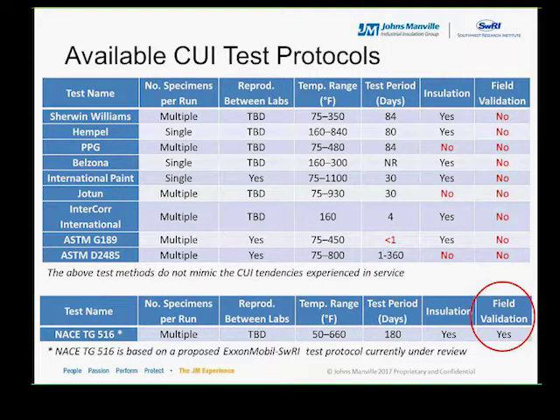Recently, ExxonMobil partnered with Southwest Research Institute to develop a test method to better assess CUI. The resulting test method reproduced field observations very well in terms of coating performance and corrosion rate of bare metals. One of the main benefits of the test protocol is that it is not a pass-fail type approach. Instead, this test protocol is to be used as a means of establishing the relative performance of coatings and insulations given a set of test criteria. The test method allows for various CUI environments that range from isothermal to cyclic operations. I will explain the developed test approach in more detail later on, and I will refer to this test method as the NACE TG516.